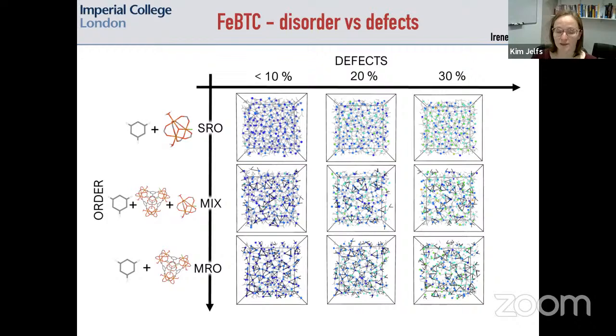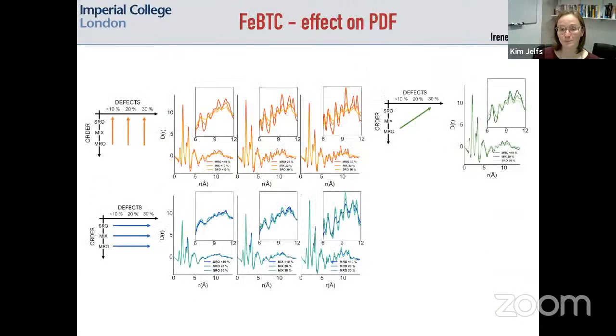Tetrahedrons are where you end up with a tetrahedron. You can see that largely these only occur when you preform them, in our case. And then the colours are showing you how many unreacted end groups, so how many defects, you've got in different areas. So we can see the various trends we're getting there by how we've controlled the simulation. And we could go back and compare this to experimental PDFs and scattering data by Adam and David Keen, and see the different trends that you get when you change defects and when you change the level of order. So we can explore trends in different directions and compare that to the experimental patterns that they're getting when they change things in the synthetic routes.